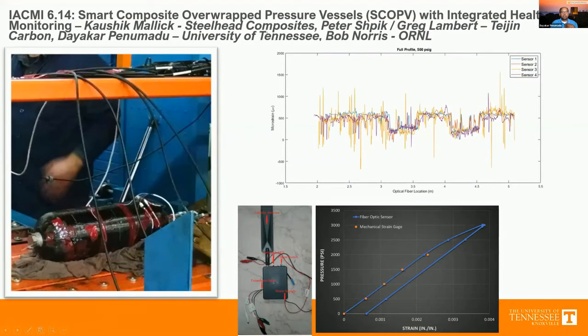This was a project led by Steelhead Composites in collaboration with Teijin, the University of Tennessee, and Oak Ridge National Labs, where we designed a 10,000 PSI pressure vessel, which used essentially a tow-preg based carbon fiber. For this application, we were avoiding wet filament winding, and we instrumented fiber optic sensors at the interface between the metal liner. In this case, it turned out to be an aluminum 6061 liner,